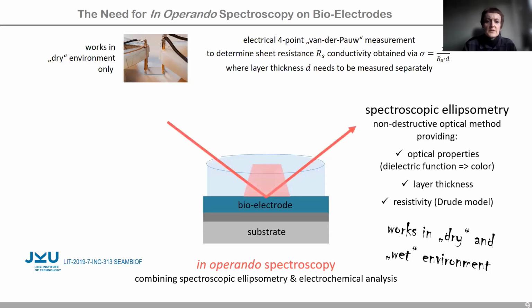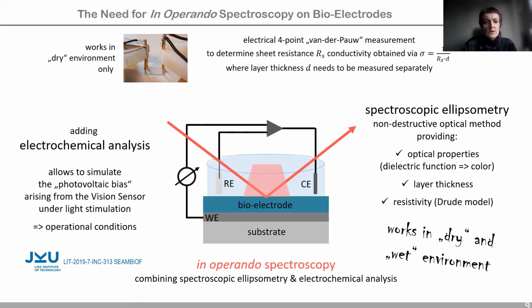Spectroscopic ellipsometry is a virtually contactless optical method, probing the sample properties with a polarized light beam. From the measured data, several pieces of information about the sample can be extracted by fitting and modeling of the data, such as optical appearance, layer thickness, and resistivity. This still is not all. The electrochemical analysis allows us to simulate the electrical bias that would come from the photovoltaic layer upon illumination. Now we can really characterize the bioelectrode under its true operational conditions.